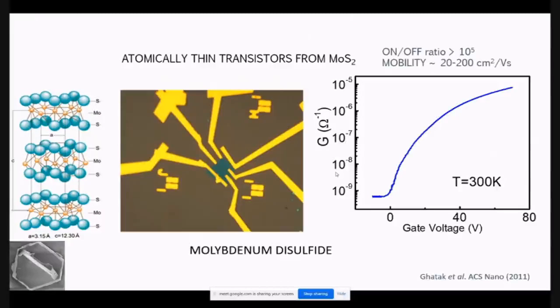Molybdenum disulfide, for those who know or are working on it, is a very interesting material. They are semiconductors, in some sense boring semiconductors because of their parabolic band structure, but they have very interesting properties. They can be extremely narrow and small. A thin monolayer of molybdenum disulfide can give rise to very large current. The conductance changes like a field effect transistor. Exactly. It is different from graphene in the sense that you can change the conductance by several orders of magnitude by changing the gate voltage below in the substrate.